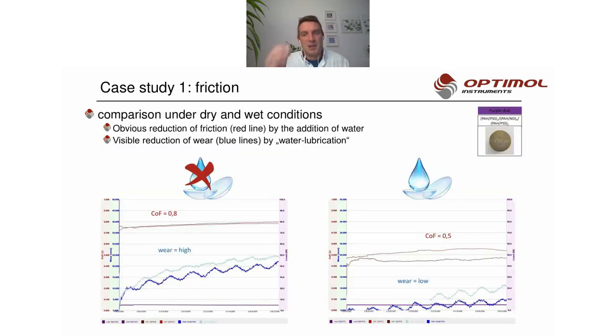And then I would like to come along with some results here. As you can see, it's an example for this purple colored coating. On the left side, you will see the conditions under dry conditions. The task was to find out if there will be a beneficial friction loss if you get in touch with water, as well as whether you will be able to decrease wear. On the left side, it's the test with the dry situation. The COF was around 0.8, and you can see on the bottom this blue line is the wear situation, which is increasing all the time during testing.